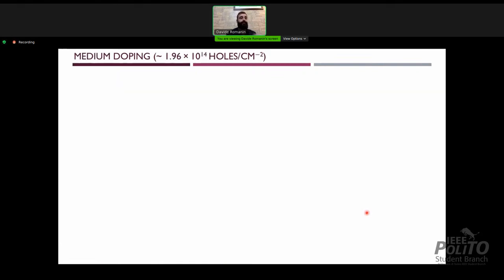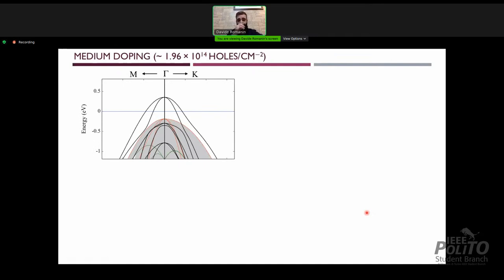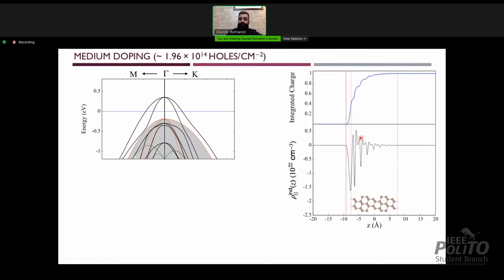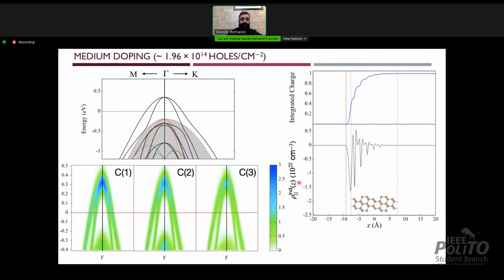Now, if we move to medium doping, we can see that this time the electronic band structure at the Fermi level is outside the gray shaded region. Therefore, we have a surface-like system. And the fluctuations of the induced charge density indeed start to be very close to the surface layers. And 75% is reached around the third, fourth carbon layer. Indeed, this time the highest contribution is not clearly attributed to one atomic layer. Indeed, we have a sort of equivalent contribution from all the first three carbon layers, meaning that we are moving towards a perfect surface-like system.